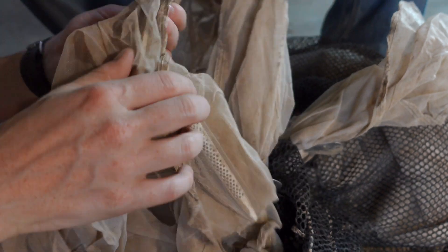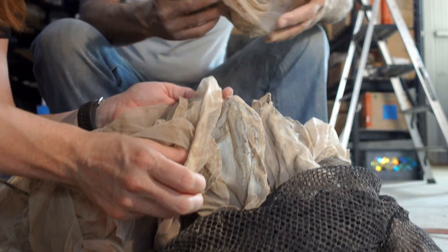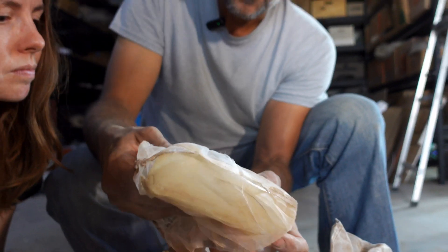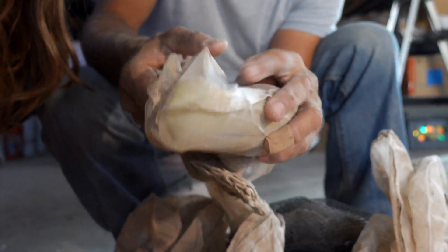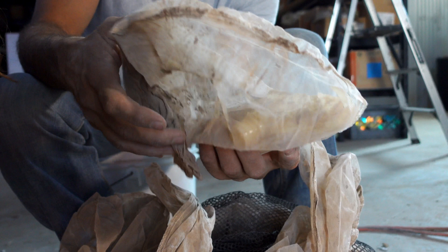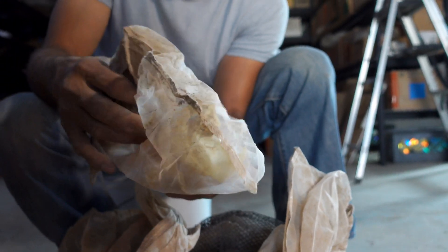At the nine-month mark, our halfway point, some of the ocean samples had almost half the material gone. All the utensils in the ocean were falling apart. You can see here it's as if you just put it in the ground — no change at all — but it's beginning to fall apart and fragmenting a little bit. The neck of the bottle is falling off. It feels very brittle; I could feel it crack in my hands when I gave it a little squeeze. In a terrestrial setting, degradation is really, really slow.